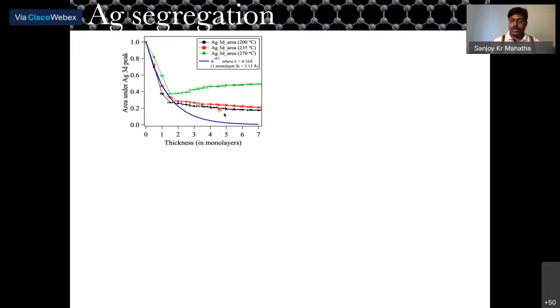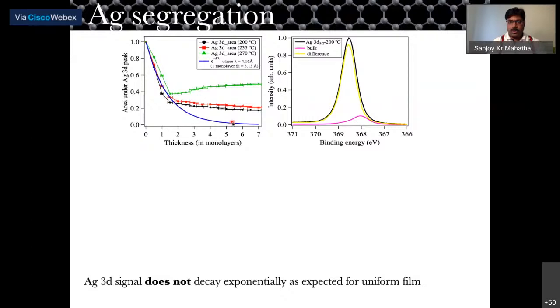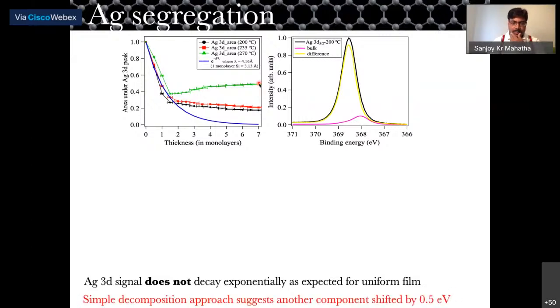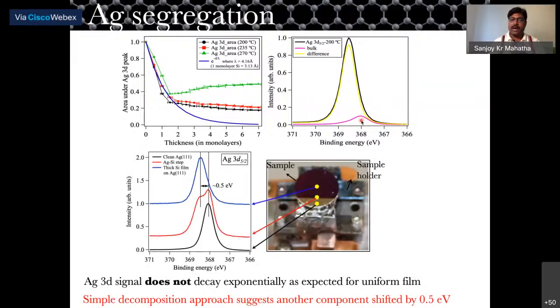None of them is matching with the exponential curve. From here, we said there could be only two scenarios: either silver is coming on top, or we are not growing a uniform layer of silicon. From there, we did a simple decomposition approach, and we found that there is another component of silver which is growing even at the lower temperature. This component is basically coming from silver on top of silicon. This is a very thick film of silicon grown on silver 111, and if we do photoemission at this point on the wedge, you can see there are two components.